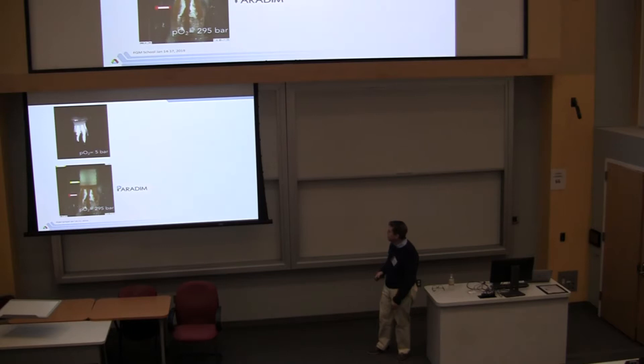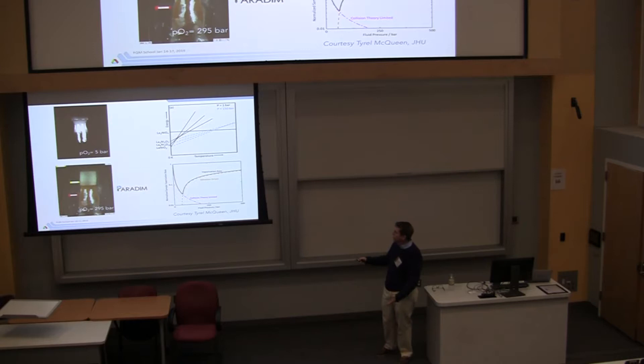There's an equilibrium constant for this. The K of P, which is drawn like this, is just the oxygen pressure or really the fugacity. Not the pressure, but we'll just, for the sake of argument, we'll call it the pressure. And so this just measures these lines. And ultimately tells you something about the stability field. So again, David talked about Le Chatelier's principle in terms of temperature with endo and exothermic reactions.